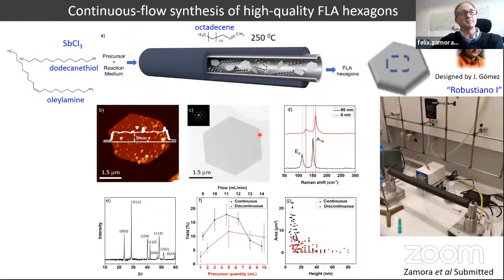And in order to overcome this problem, in collaboration with Julio Gomez, who designed this continuous flow reactor, he called it Robustiano the first because his steel reactor is very robust. We started with the same precursors, and we submit the solutions to this temperature, adjusting the flow to have this temperature for a short period of time. Immediately after, we collect the material and decrease the temperature. And the result of that is that we produce these nice hexagons.